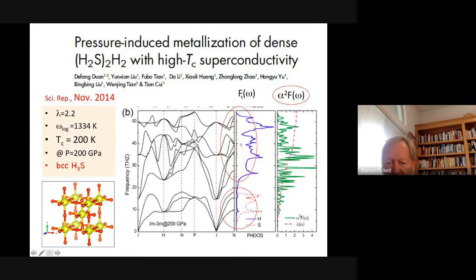And I'll just show you here the phonon density of states, and all of these phonons are hydrogen with its small mass, its frequencies are high, and sulfur is the dashed part here. So they happen to be separate, and that's actually an important feature for understanding what's important for superconductivity here. And that was the main focus of that paper I mentioned earlier.